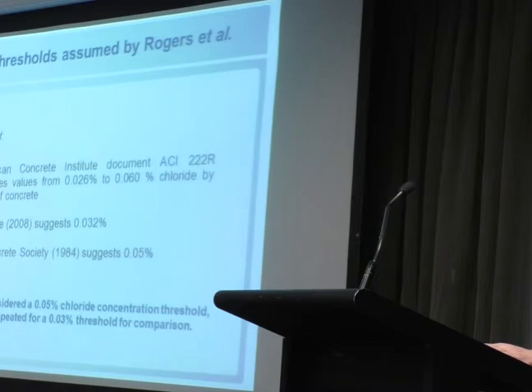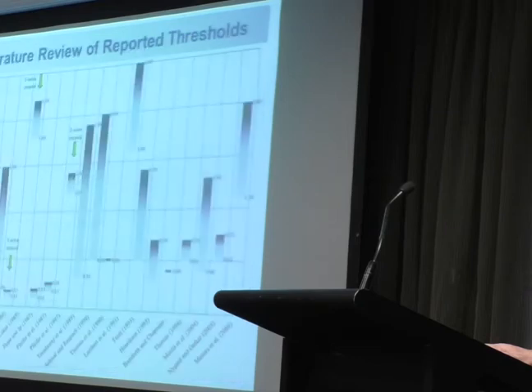And they're in line with the literature cited, but if you take a wider view, and this is data from the US Federal Highway Administration, there is a whole range of data. That's Rogers' suggested maximum threshold, and as you can see, some of the data sits below that, some of it sits above it, and there is an enormous range, orders of magnitude, in the values that have been cited by different researchers. I haven't followed it up, but I would suggest that the very precise values down here are probably by electrochemists putting rebar in simulated pore solutions, and that the broad spread is by people who've gone out and tried to interpret initiation of corrosion by inspection on actual structures.